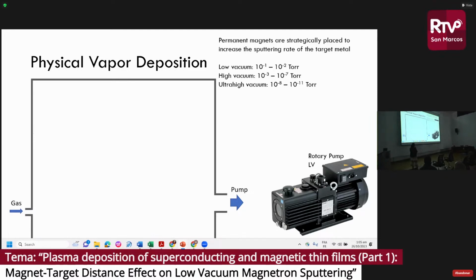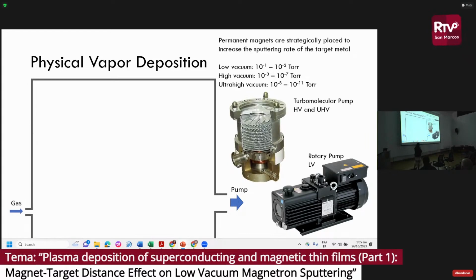Low vacuum is if you're just going to use a rotary pump. High vacuum is if you're going to use another pump called the turbomolecular pump. It's actually composed of rotors and stators. So these are alternating blades. Every other layer is moving, and the next layer is actually static. And it helps bring out the gas from inside. Let's say this is the chamber. From this part of the chamber, it helps put away the gas outside and it gets pumped out. So that is how pumping happens for high vacuum. Now, if you would like to have ultra high vacuum, you would like to heat up the entire chamber and also pump down for a few hours to up to a few days.